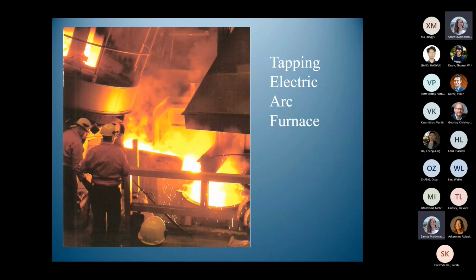So the steel never really gets over that first pour. A lot comes out, but a lot stays in. And this is why our steels will never be much good while we have this technology of melting in a furnace and pouring through a height of 3 meters or so into a ladle. And there's got to be some serious rethinking about how to redesign steel making equipment.